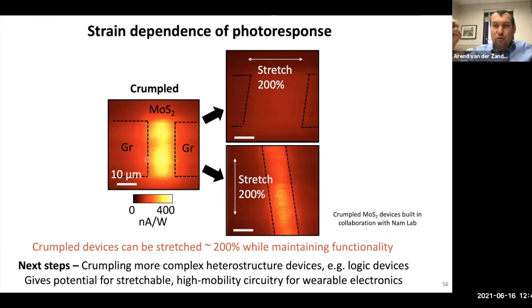And now as we stretch it, we can stretch it along one direction or the other, the intensity of the responsivity is changing, but we can still see it's lighting up just a little bit inside of the channel, even when we stretch it by a lot. This tells us that the device still functions, even when we stretch it by 200%. This means that we now have a new way of creating stretchable and yet high performance electronic systems.